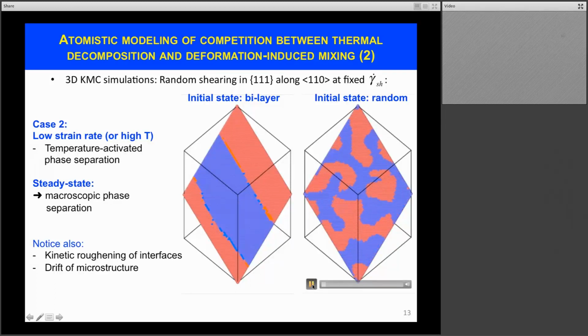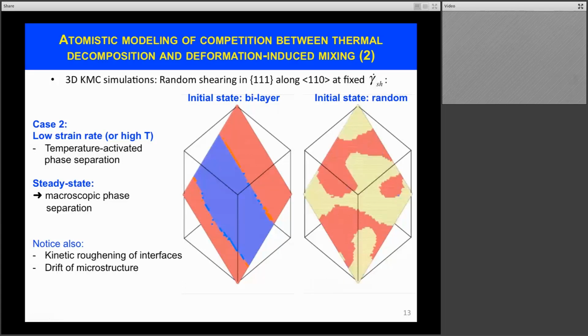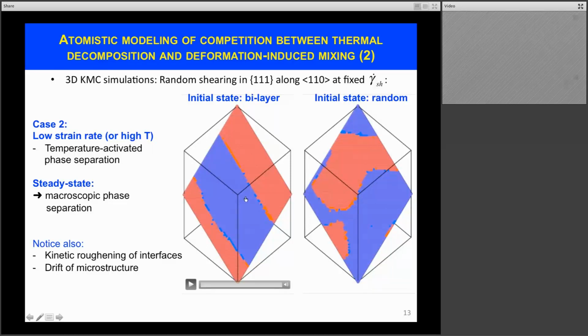And on the right-hand side here, starting from a solid solution, now we see that the system forms two phases, and slowly it will evolve and reach the same steady state as the one depicted on the left. That is, again, we have a unique steady state here. The simulation didn't run long enough, but in this particular case, the steady state is one where we have macroscopic phase separation between the blue phase and the red phase. And it's reminiscent of this macroscopic phase separation in copper-silver mixtures ball milled at elevated temperature.